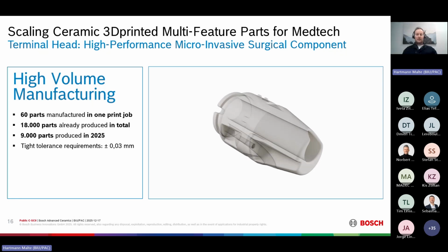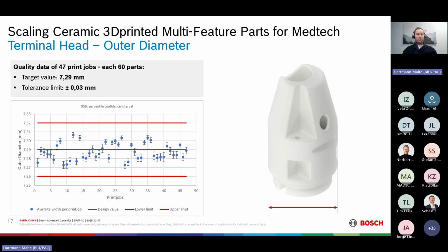The data that came out is shown here. Overall, that's quality data of 47 print jobs, as mentioned, each 60 parts. The target value for the outer diameter, which can be seen on the right side here, was 7.29 millimeters. And actually, all of those values are within specification. The XY feature tends to have a higher variation within each print job due to overpolymerization, but we see very good repeatability of print jobs, especially if we consider all those potential influences. On average, we can say the confidence interval is 4 micrometers and the standard deviation is 14 micrometers.